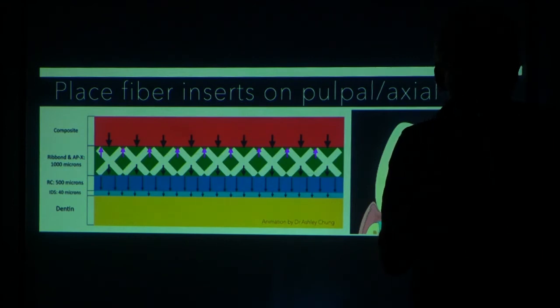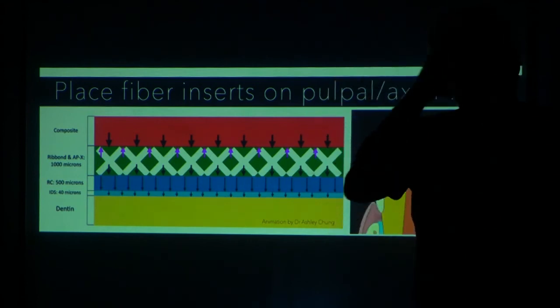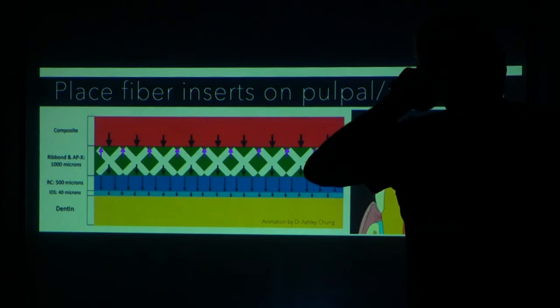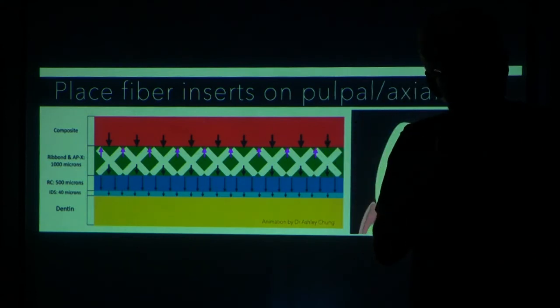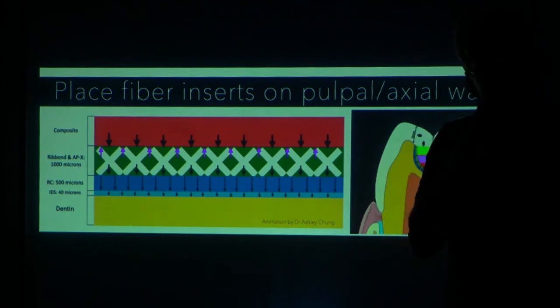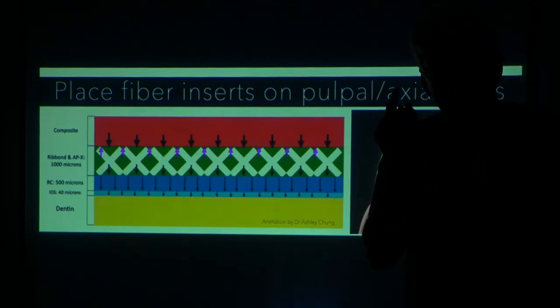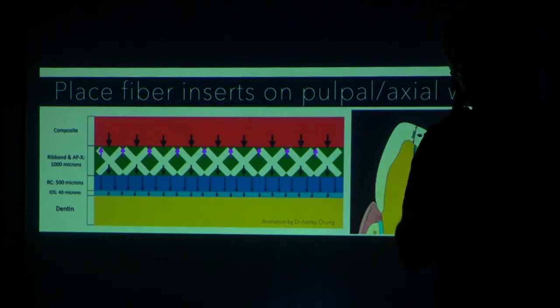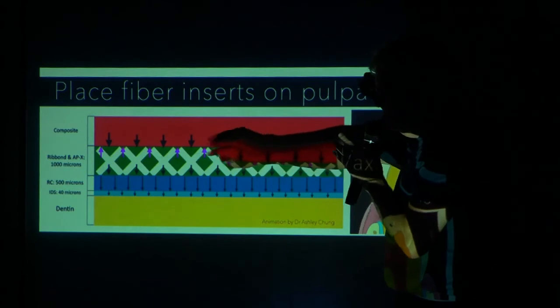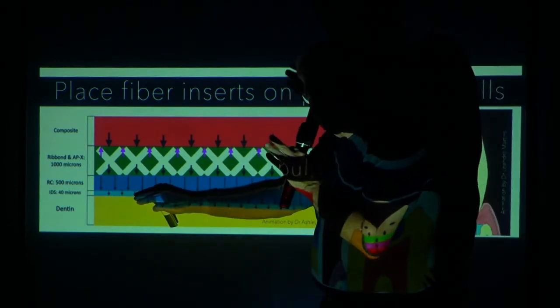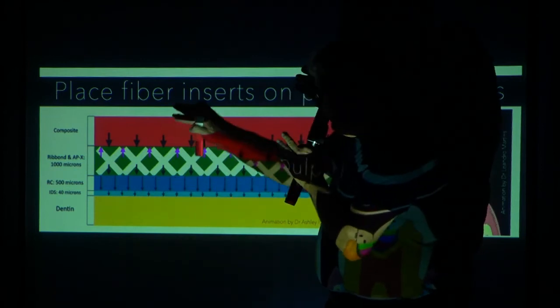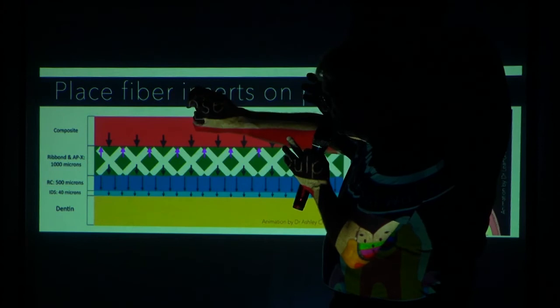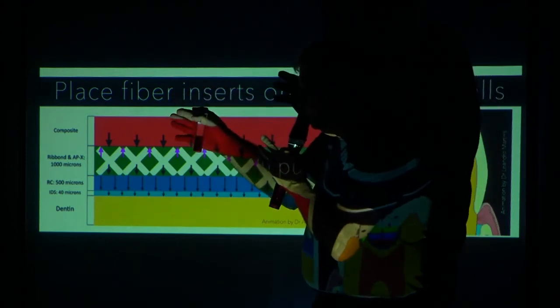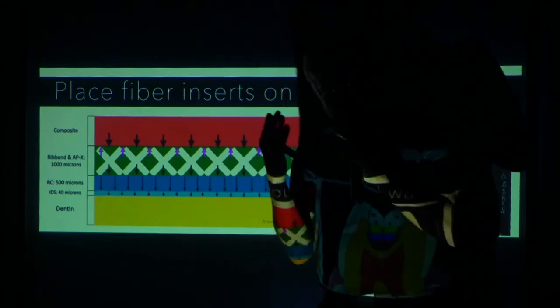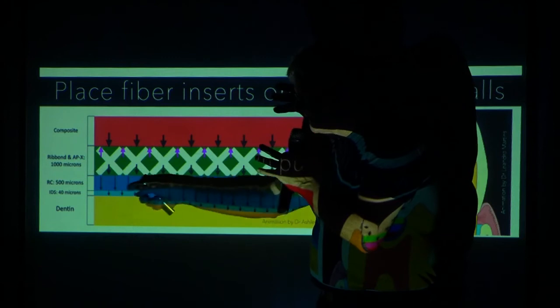Well, Erkut found that when they put this fiber ribbon on both sides of the endodontically treated tooth, not only did it act like a post, but it decreased the stress and guaranteed the bond and the seal. All of the other post systems failed. They all had leakage, but the ribbon post did not, and the reason is that we had this separation of the fiber, and the hybrid layer was never disrupted. It always had a seal, and the middle of the composite in this endodontically treated tooth, that massive composite, polymerized strongly. It acted like a composite post, but it had no negative effect on the hybrid layer, so it kept the seal.